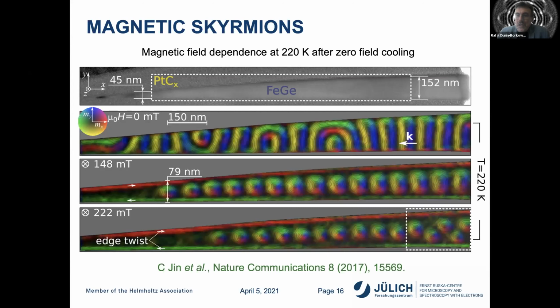So now I show the results of magnetic states recorded in the region of the magnetic stripe shown with the white dashed rectangle in the bright field image at the top. In zero applied field, we have what is called a helical magnetic structure, which extends right to the very edges of the magnetic track. And then in the presence of an applied field, a single row of skyrmions forms.